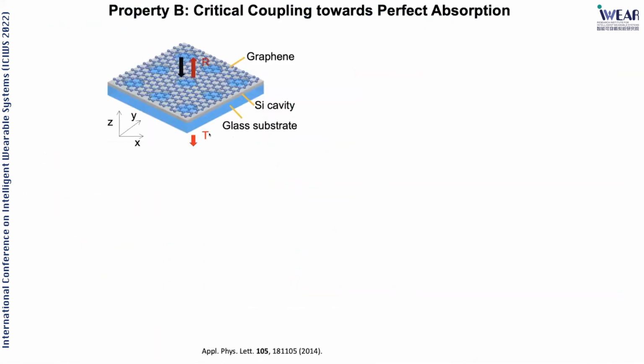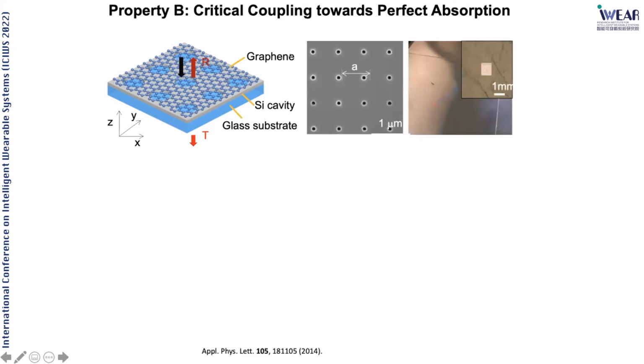The second aspect based on this photonic crystal structure is so-called perfect absorption, meaning now you don't need a very thick layer. Especially, it's very important for wearable, for bio-integrated structures, where film thickness probably is one of the limitations in some cases to get into this flexible and thin film form factor platform. Here, the example we have is a thin layer of graphene. Typically, you can only absorb 2.3% of the light. By coupling this into a single layer silicon structure on a glass substrate or any polymer substrate or flexible substrate, if we design it right, you can see some SEM image and also a micrograph of this structure here.